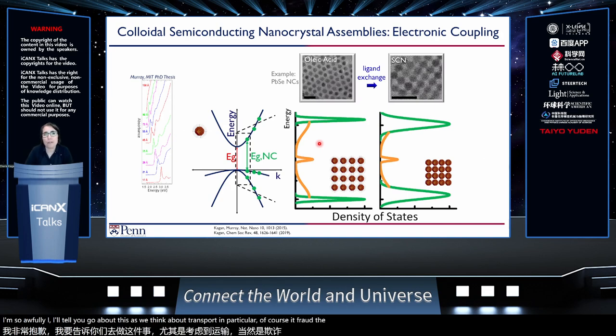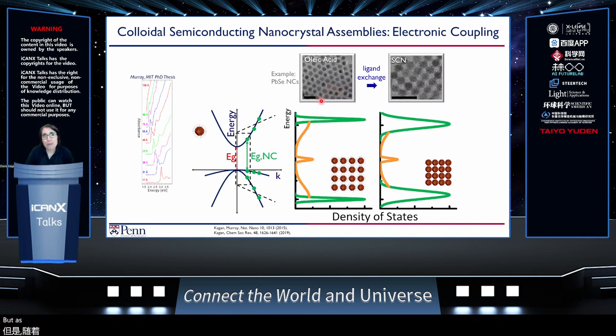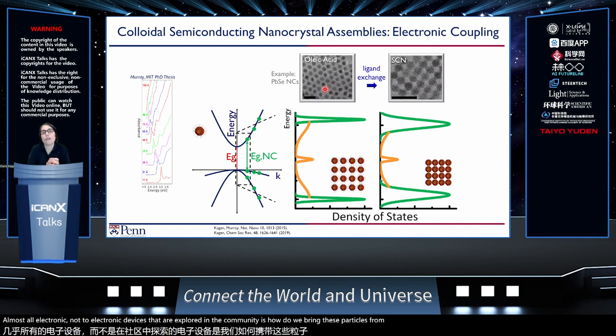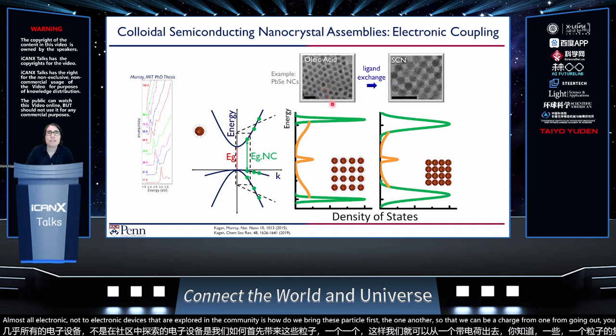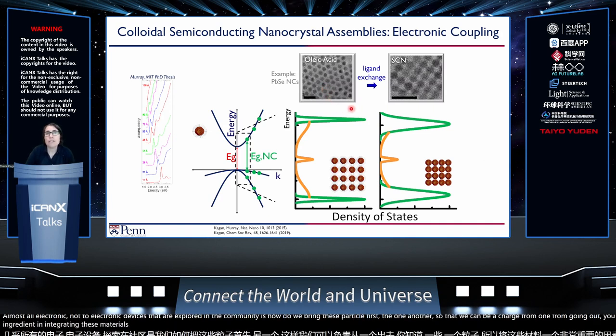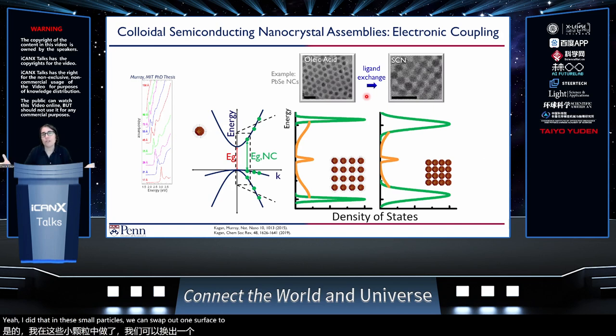Of course, it's broadly important and the origin of also developing core shell materials to manage and passivate these states as we think about their luminescence characteristics. But I said it's very hard to move charge between these particles because of these long ligands. And so what's been used in almost all electronic and optoelectronic devices explored in the community is to bring these particles close to one another so that we can move charge through an ensemble of particles. A very important ingredient in integrating these materials into devices is what we refer to as ligand exchange, the idea that in these small particles, we can swap out one surface chemistry for another ligand.